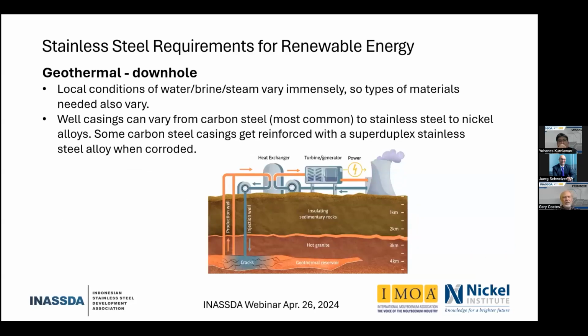The downhole conditions, the local conditions, vary immensely. Of course, everybody would love to use carbon steel, and many of the plants actually do. You can use guidelines similar to those used for oil and gas production. NACE MR0175 / ISO 15156 can also be used to help determine the appropriate material. Some of the other plants will use stainless steel, and there are even some that use nickel alloys. I'll mention one about that shortly. There are some cases we've seen where the casings will corrode after a while, and you reinforce them typically with a super duplex stainless steel alloy. The reason for that is the compatibility from a thermal expansion point of view, and you also get the high corrosion resistance.